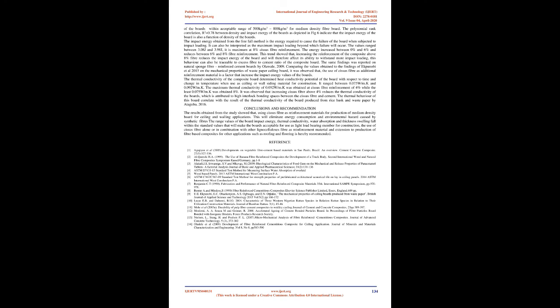The thermal conductivity of the composite board determined the heat conductivity potential of the board with respect to time and change in temperature when used as ceiling or wall siding material for construction. It ranged between 0.075 W/m.K and 0.092 W/m.K. The maximum thermal conductivity of 0.092 W/m.K was obtained at Cissus fiber reinforcement of 4% while the least, 0.075 W/m.K, was obtained at 8%. It was observed that increasing Cissus fiber above 4% reduces the thermal conductivity of the boards, which is attributed to high interlock bonding spaces between the Cissus fiber and cement. The thermal behavior of this board correlates with the result of the thermal conductivity of the board produced from rice husk and waste paper by Akinbosoye, 2016.